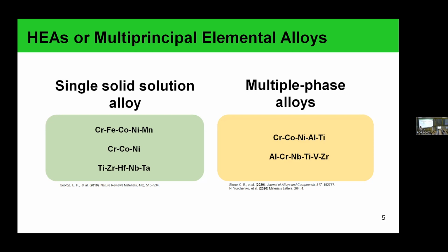In the first group, there is the 5-component system, which was the first demonstrated high-entropy alloy, and the high-entropy alloys with 3 components. Also, there is a new direction which grew from the field of these high-entropy alloys: refractory high-entropy alloys with refractory elements in their composition, and also the composition presented by the group of the Belgorod State University, which also used refractory elements. It is like the multiple phase alloys. These two alloys demonstrate extremely great characteristics at elevated temperature, but with limited ductility.